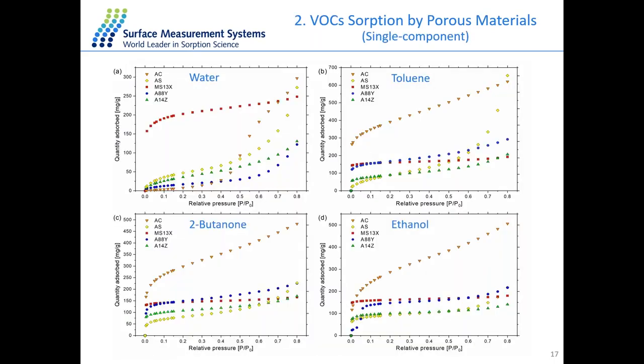From the first set of data for the single component isotherm, we measure the DVS isotherm with one organic vapor or one probe molecule only, and we get the isotherm for different types of porous material. The water and toluene probe molecules just represent a wide range of potential VOCs in the air with different polarities. The y-axis is the quantity or amount of the vapor molecule adsorbed by the porous material in milligram per gram.